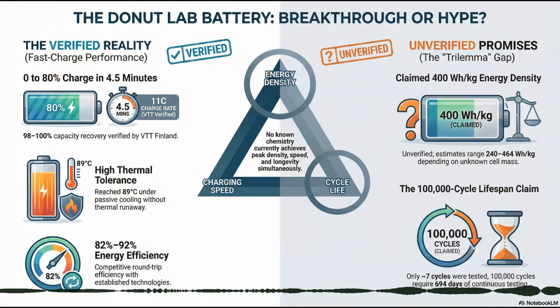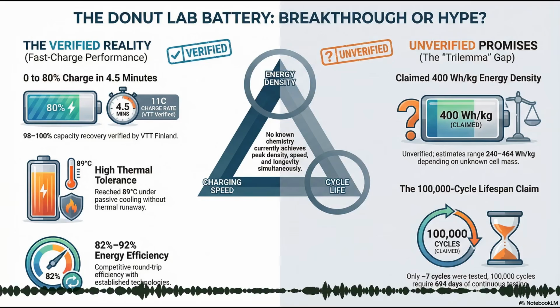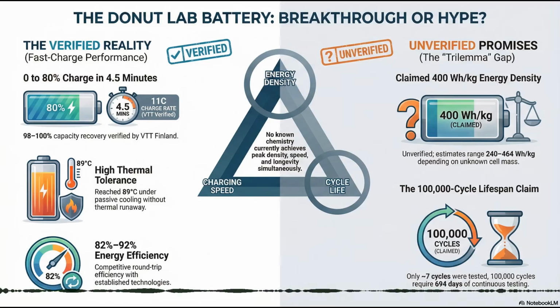A lot of these academic breakthroughs happen on coin cells, CR2032s with micrograms of active material. Right, where heat dissipation is basically irrelevant. Exactly. Scaling from a coin cell to a 26 amp-hour pouch is where 99% of novel chemistries die. They fail due to resistive heating, uneven current distribution, edge effects. This is a relevant automotive-grade format, and they absolutely hammered it.